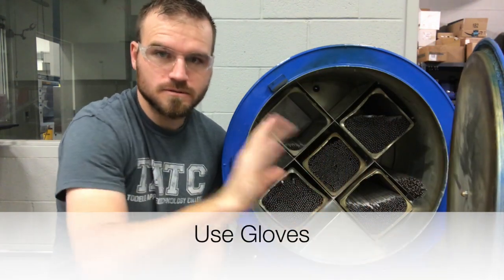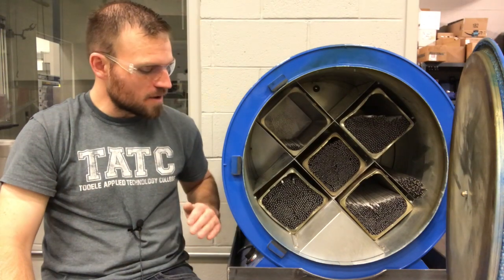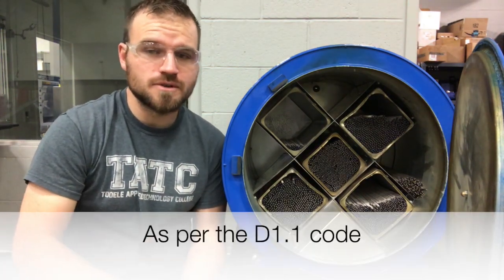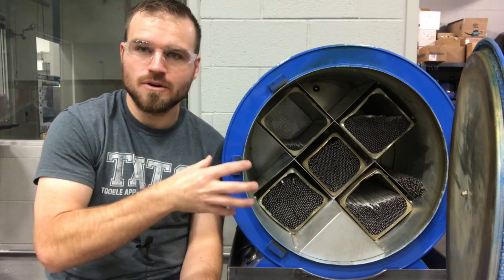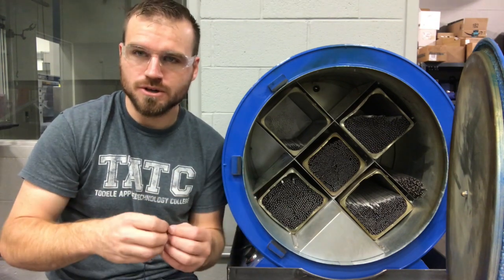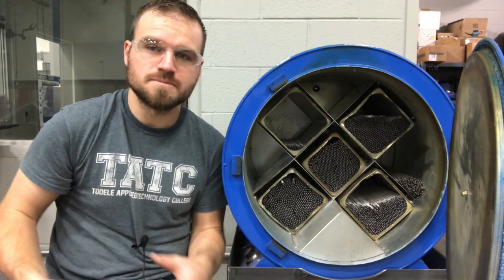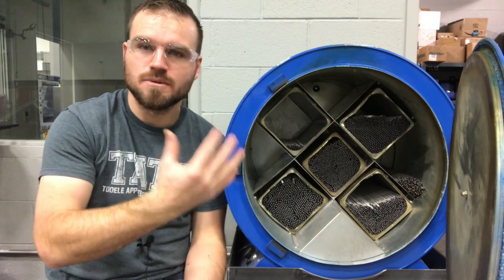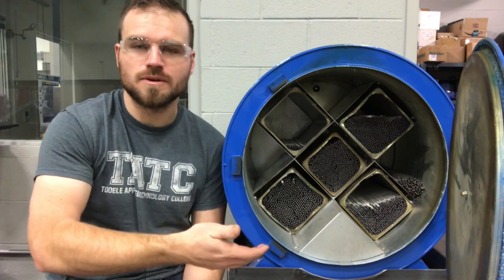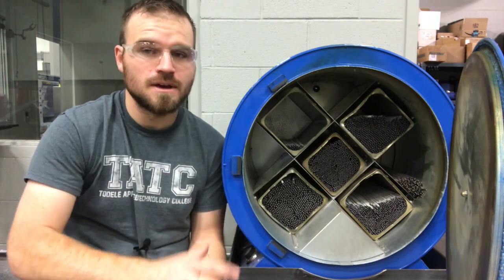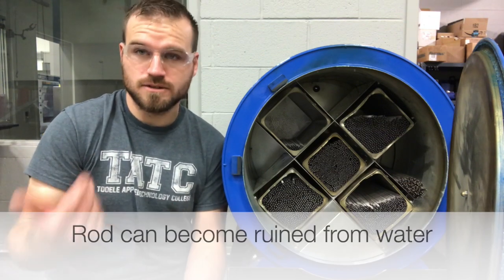Let's move on to our welding oven. You can see that we're storing all of our rod here in this oven that is required to be in there. I typically have my rod oven set anywhere between 250 to 300 degrees Fahrenheit. Remember when I was saying about how to open that case, you have about two hours to weld with it. What happens is that outer flux on that welding rod can collect moisture, and then when you go to weld with it, that moisture will get into your weld. It's kind of the same thing is true about your welding rod oven. If your welding rod has been out of the case, then you need to get it into your welding rod oven and it needs to bake in here for a little while. Usually it's about two hours, depending on what degrees you have your rod oven set to, or how much welding rod's in there, or the thickness and size of those welding rods, or even the type. Just kind of look into that and make sure that what you're using is correct. What I usually do is I try to bake all my welding rod if it's been outside for a while for about two hours before we weld it or do anything with it.